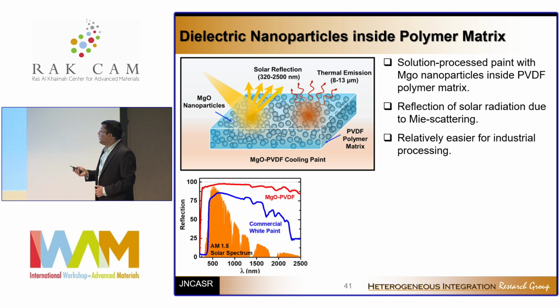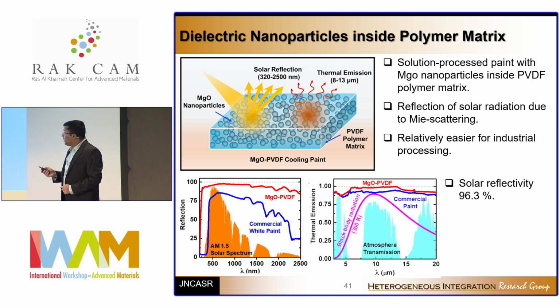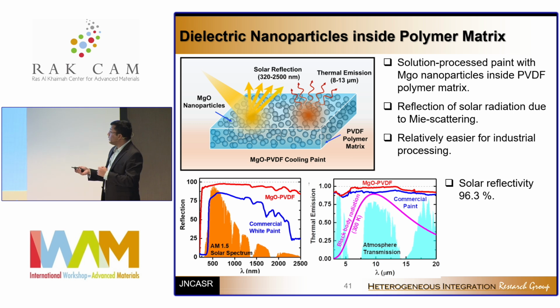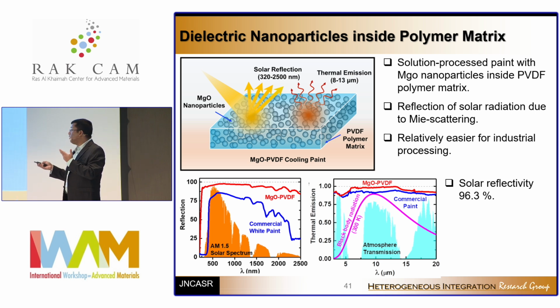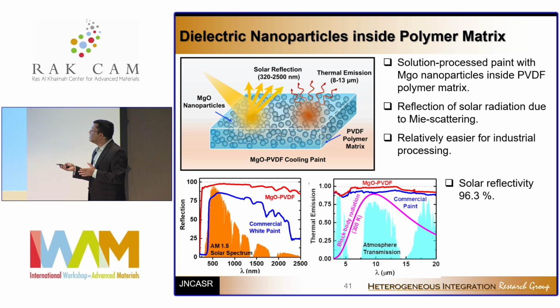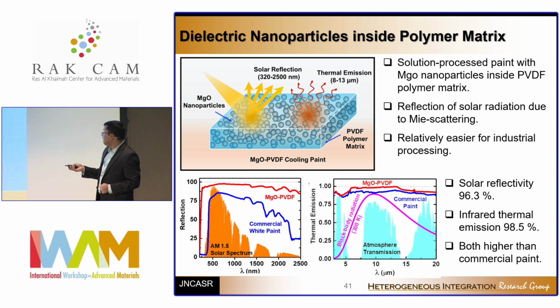So if I show you the reflection spectra, as you see, the MgO PVDF has a really high reflection spectrum. I think the total solar reflectivity is around 96.3%, which is very high even with respect to commercial paint. The infrared emissivity is also close to 1 in this wavelength range, and that arises from the MgO stretching frequencies and molecular vibrations from the PVDF also. So this gives you a high solar reflectance and a high infrared emittance.